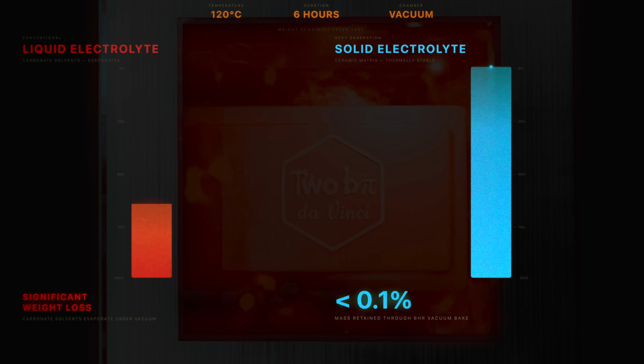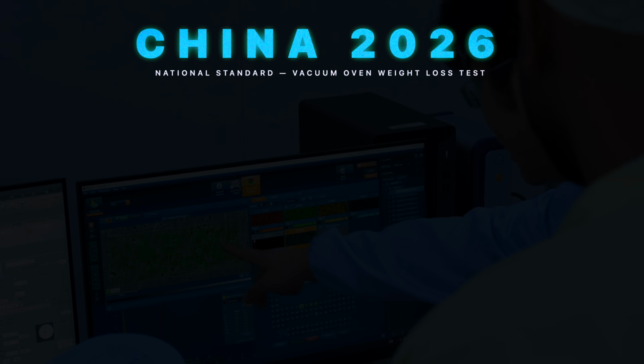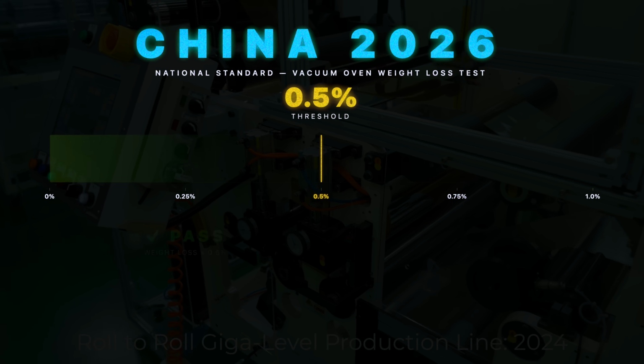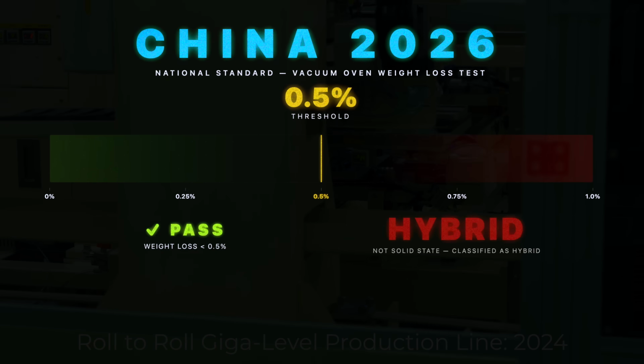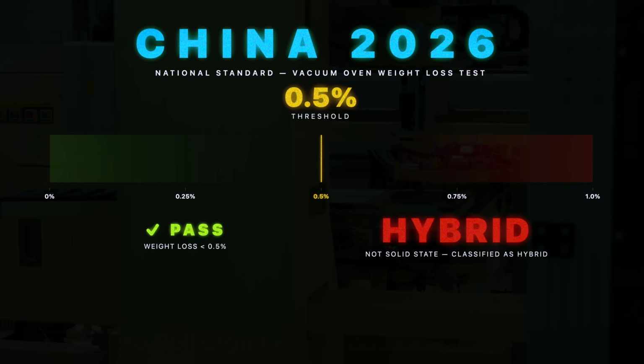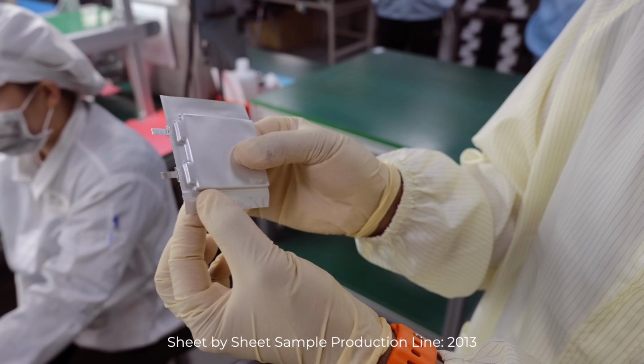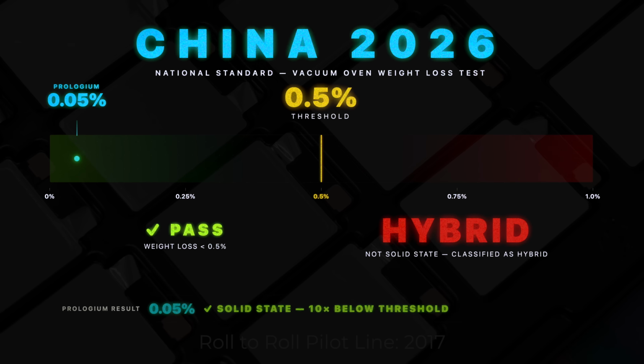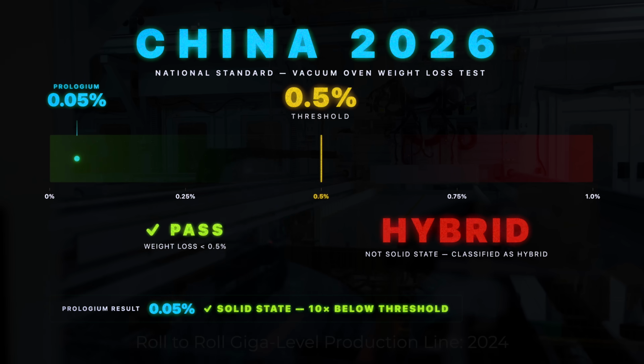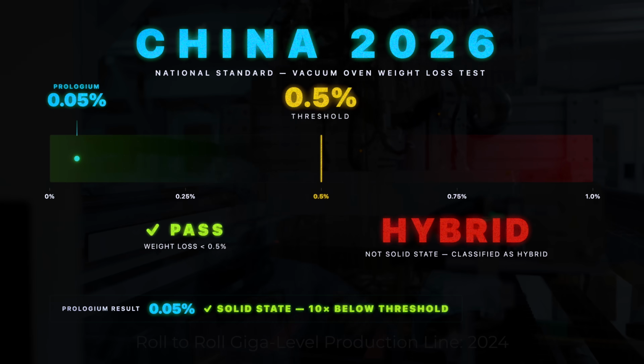A solid electrolyte loses less than 0.1% of its weight. To pass China's 2026 national standard, your cell has to lose less than 0.5%. Anything more, and you're classified as a hybrid. ProLogium's Gen 3 cells pass with an average weight loss of just 0.05%, a full order of magnitude below the threshold.